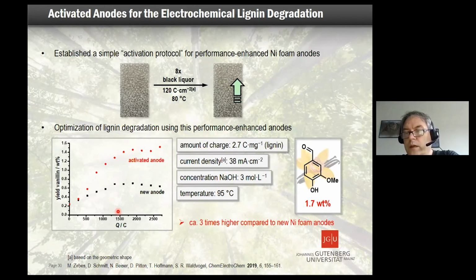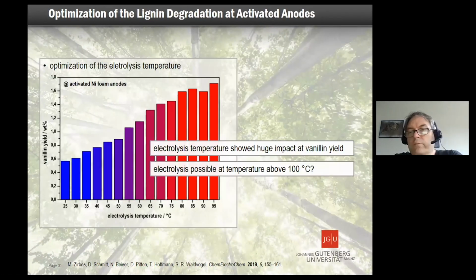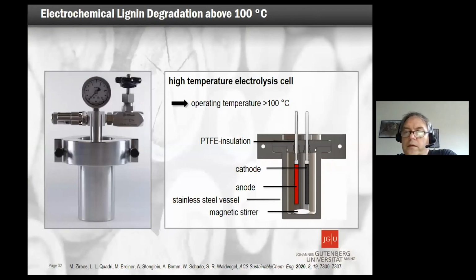At that point, we had 1.7 weight percent vanillin out of the lignin. And the question is, can we go even better? It turned out, if you go to higher temperature, it increases as well. Therefore, with the knowledge we had before, we went to higher temperatures. And this was maybe more or less the key. What is the reason for that? You usually have an oxidation of the lignin, and the particles interlink, and it's not floppy enough.